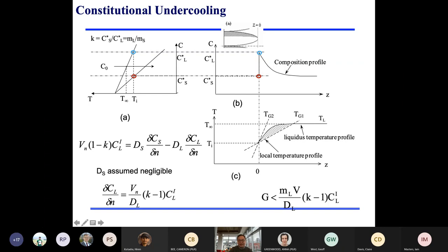So you can apply different thermal gradients to either avoid this columnar to equiaxed transition or promote it. For example, in directional solidification, if we want to grow single crystals, you will normally use a high thermal gradient and low growth velocity, essentially the TG2 condition, and you would not allow any grain to form ahead of the solidification front. But if you want to promote it, for example in a continuous casting process or even a welding process, you can minimize it by introducing heterogeneous solidification, either by alloy design or by process optimization, right?